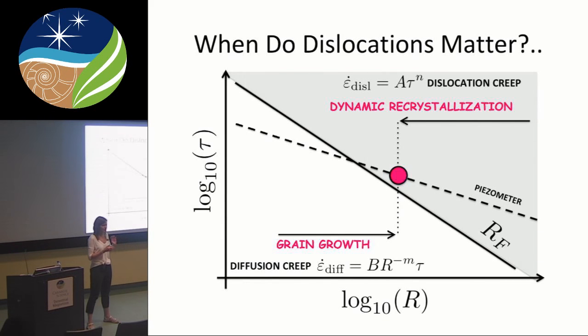We first looked at matching the theoretical model to modern Earth-like shear zones, and just looked at how temperature determines the grain size distribution across the lithosphere, so across the different temperatures on modern Earth. And then once we, to some degree, calibrated the theoretical model to that, we tried to apply that, including the time evolution towards that state, for early Earth-like conditions. And the theory we tried to test is the collapse of passive margins. So you have this classical Wilson cycle where you have opening and closing of oceans. And Wilson would have predicted that your subduction initiation, a very important point in the initiation of plate tectonics as a whole, is how to initiate subduction. Still one of the big, most interesting questions, perhaps, in geodynamics.